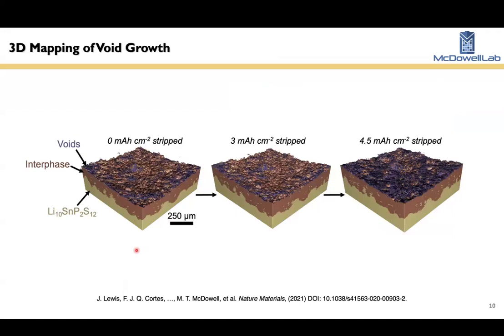So this is now a 3D view of the segmented data set from these X-ray tomography experiments. Here's a pristine portion of the interface. We're looking at the solid electrolyte here, and lithium is above this solid electrolyte. It's transparent in these views. The purple voxels are voids or lack of contact between the lithium and the electrolyte. So as we start, there's some voids. As we strip the full cell here, you see that at the end of the stripping experiment, there's quite a lot of voids that are present. There's a lot of purple that is covering the interface.